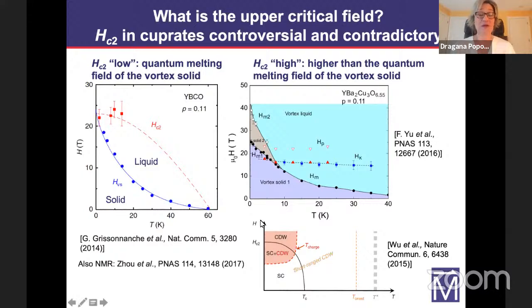To illustrate this problem, here are a couple of examples from relatively recent papers that report measurements on exactly the same material, YBCO, at exactly the same doping, but the conclusions that were reached were very different. Here, for example, it was argued that the upper critical field is basically the same as the quantum melting field of the vortex solid. In other words, that in the limit of low temperatures, there is no vortex liquid. And here it was argued just the opposite, that actually the experimentally accessible magnetic fields are not high enough to suppress superconductivity, that the vortex liquid extends to much higher fields, way beyond this quantum melting field of the vortex solid.